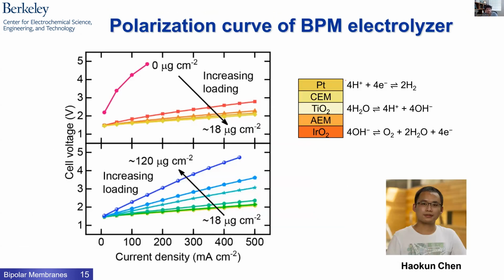So the first thing we did is kind of obvious. If you have a catalyst, it would be nice to know how much the rate of the reaction depends on how much catalyst you have. So as you load up catalyst in this interfacial region, it gets better. The voltage I need to drive this overall cell, this is the total cell voltage, includes that for driving the thermodynamics, which is about 1.23 volts.